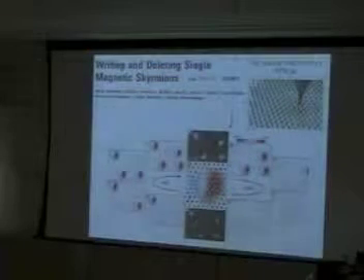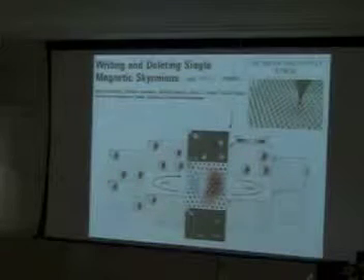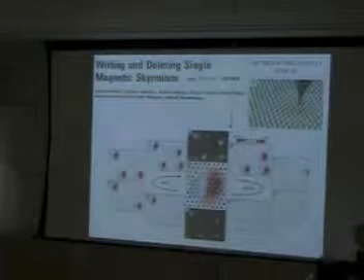So certainly this is an example. We are also now making simulations by introducing defects, some cuts in the magnetic film, and it appears that we are just patenting this mechanism. It seems that by cutting the film with a very sharp shape, it is possible, simply by passing the current through the film, to create skyrmions at some points on these cuts.